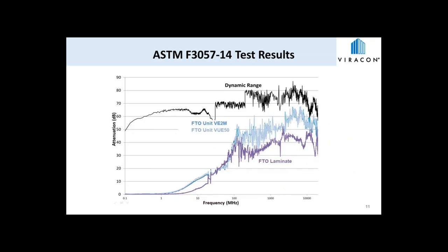So moving on to the ASTM method results. Again, only three of the samples were tested, really focusing on the FTO conductive coating. So the FTO laminate, and the two FTO units. Keeping in mind with the ASTM method that the unit size is three times larger, and the full range of frequencies was tested from 100 kilohertz or 0.1 megahertz all the way up to 20 gigahertz. As stated earlier, though, the same basic test method as the IEEE test is used.